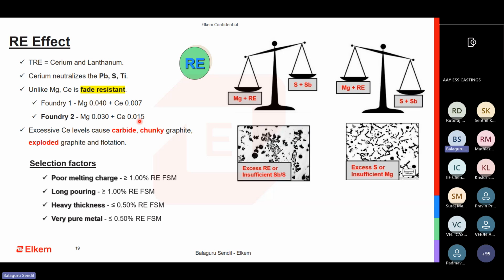The nuclei it has created, the ductile iron nuclei it has created, you just need to activate them to grow to a correct shape and size by correct inoculation. So the cerium is very, very important. You should ideally have an FSM with cerium, a rare earth, in it, so that you have fade resistance also. At the same time, it neutralizes tramp elements. The negative side is that the most common thing we see in the industry is that if I have cerium, then I will get chunky graphite. That is a common thing communicated in the industry, which is also in a way correct, but not correct. What do I mean by that?